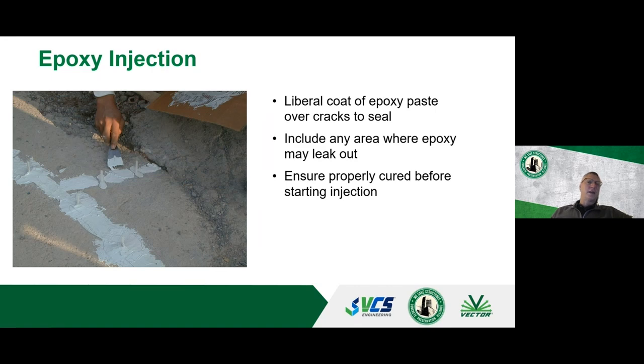And the reason you're doing that is the epoxy paste itself has no structural value to crack repair, but you're creating a seal so that when you're injecting the resin, because you're going to be injecting this resin at a high pressure, you want to make sure that the resin is going into the crack and down through the crack to repair it. You don't want it coming out through the crack itself.